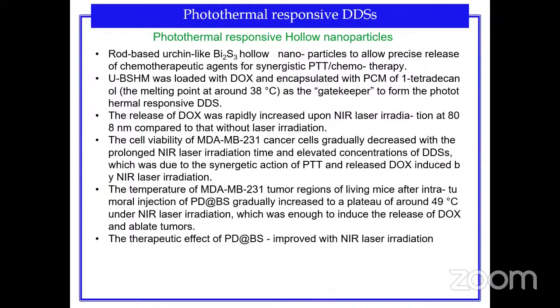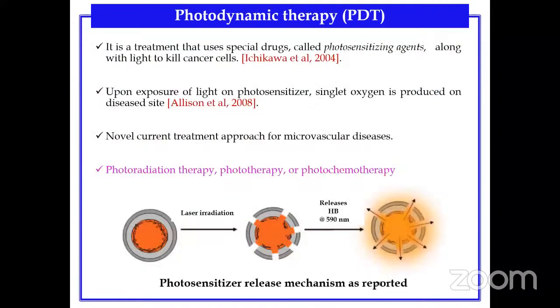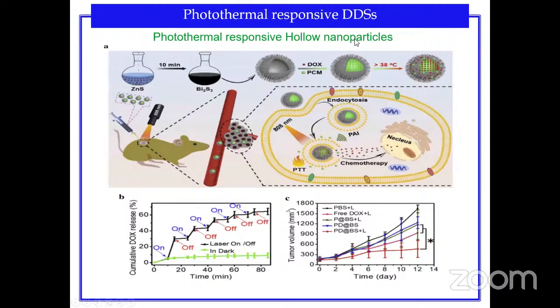That light-activated system will be able to generate heat due to the presence of bismuth sulfide, which killed the cancerous cells of MDA-MB-231. The temperature was raised up to 49 degrees Celsius under the near-NIR region, which is sufficient to induce the release of doxorubicin and ablate the tumorous cells. So this is the photothermal responsive hollow nanoparticle: initially we make the bismuth sulfide, which is put onto the surface of these systems. Then on exposure to light, the drug is released and heat is generated; both are responsible for the cancerous cell death.